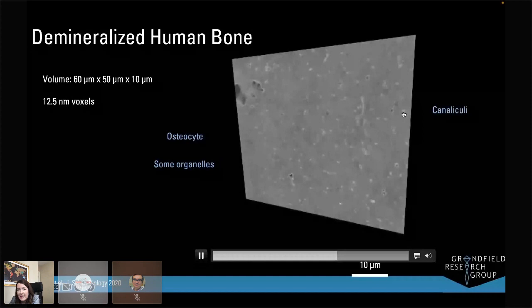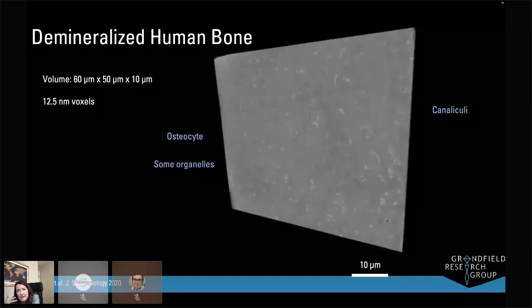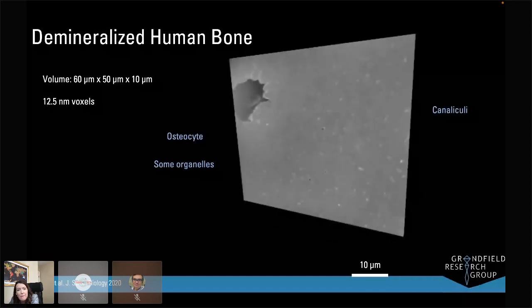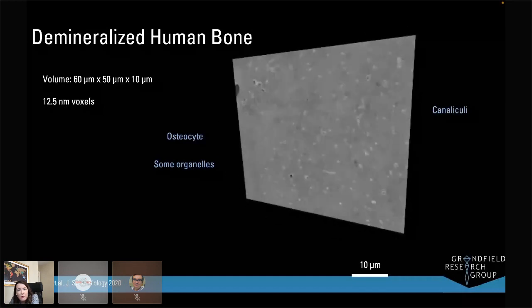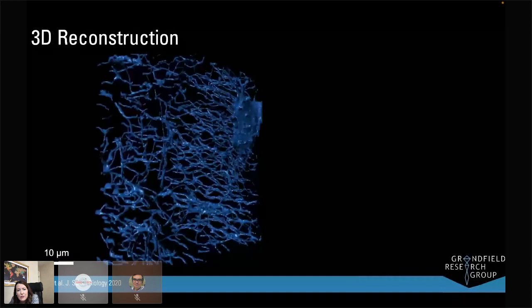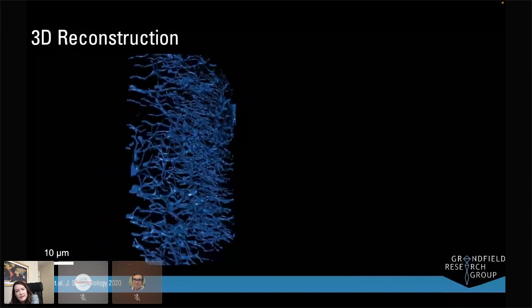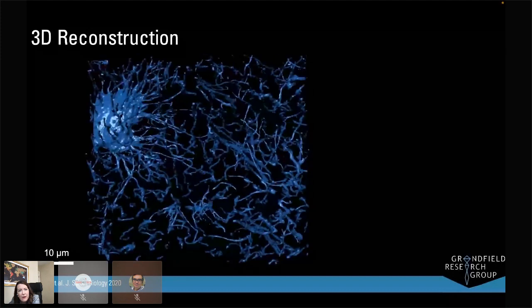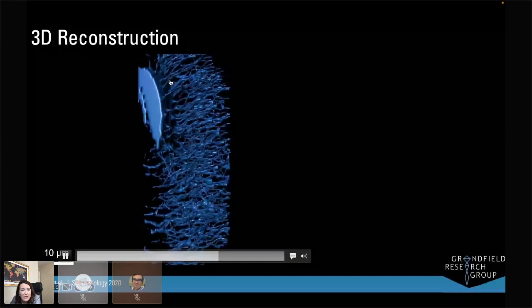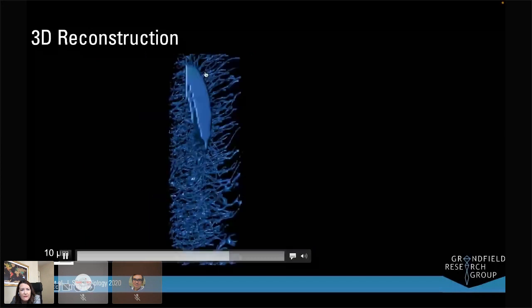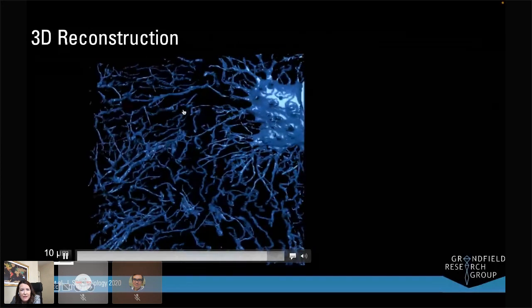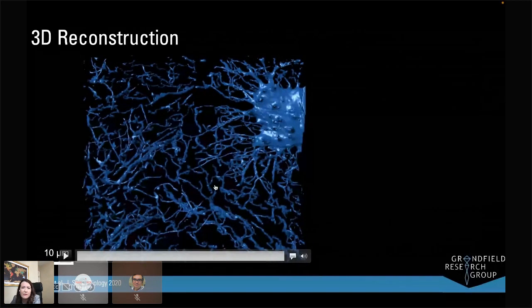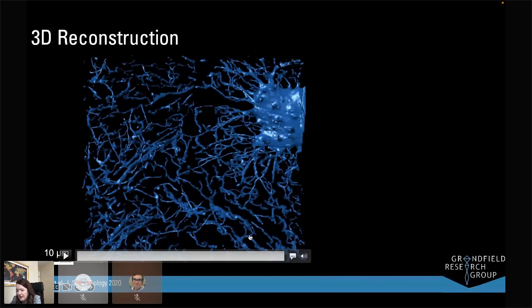We can take these 2D images, put together into a 3D stack, and reconstruct and segment some information from this. One nice thing we can do is segment out the cell networks, and you can see this really widespread interconnected cell network. We have one cell that's visible here, but there's also another cell outside of this data set, so we actually have the zone connecting the cell networks between two cells inside this data.